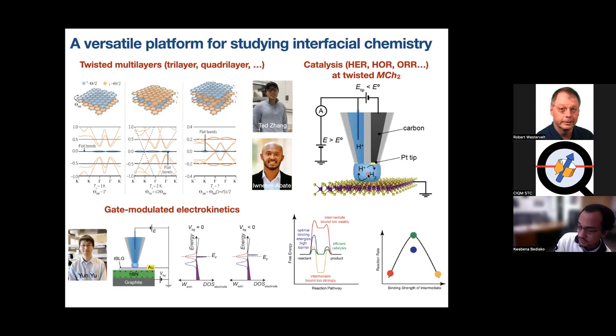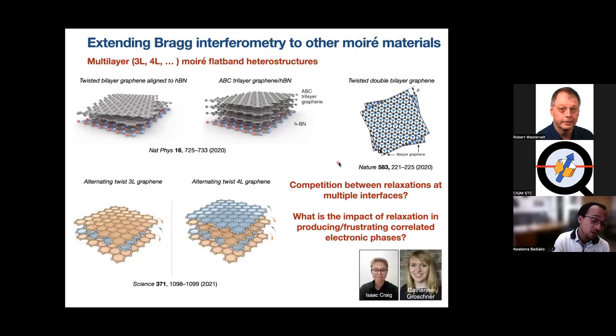Okay, now we're taking this in the direction also of catalysis and saying, well, usually when we want to tune the catalytic activity of a surface, we change the composition of the surface entirely and try to use that to change the binding strength of some intermediate, right? Well, now we have a way of reconfiguring the band structure of a material without changing its chemical composition, just by changing the twist angle and using that as a descriptor for the reaction rate. And so what we're really excited about is now, and Tim is working on this along with Ted, using this as a way to control interfacial catalysis.